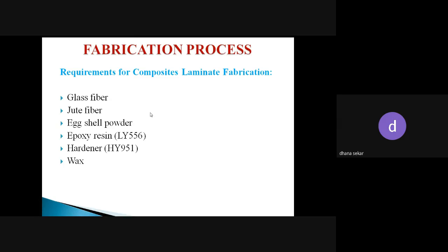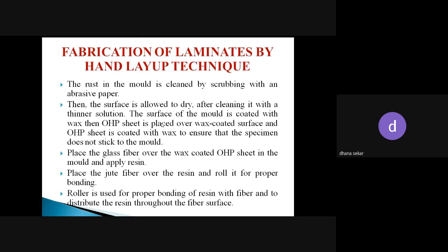Next, the fabrication process. The components required for fabrication are glass fiber, jute fiber, eggshell powder or eggshell additive, epoxy resin, hardener, and wax. Here we have chosen 350 GSM bidirectional glass fiber, and jute fiber, which is also bidirectional. We used eggshell additive, and epoxy resin and hardener as prescribed in the ASTM standards. We followed the ASTM standard, and we fabricated the laminate by the hand layup technique.